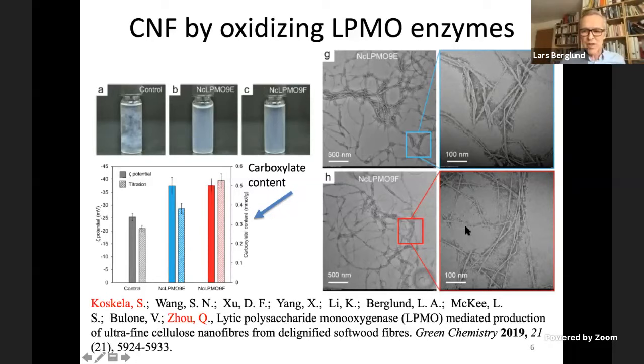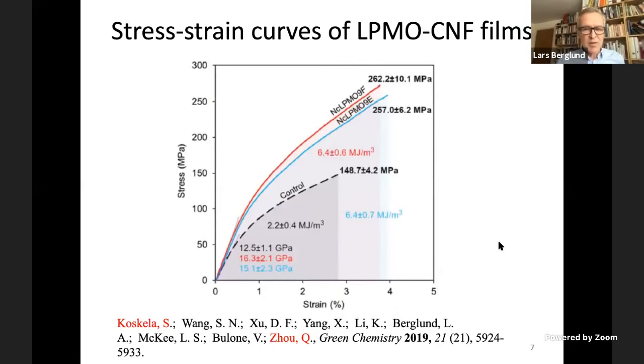So the high resolution TEM image on the right-hand side, you see that the fibrils are actually very, very fine. And the properties of films from these LPMO treated pulp fibers are actually quite good. So it's the same idea as with enzymatically pre-treated pulp, where you make fibrils, and you actually get slightly better properties. The strength is something like 250 megapascal and with high modulus. So this is a new approach towards making fibrils.